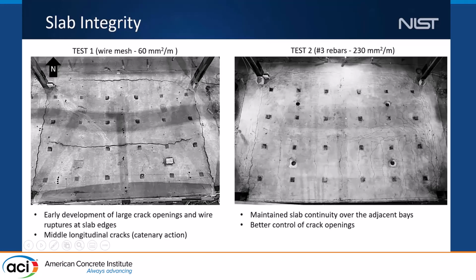Here is test number 2, reinforced with number 3 rebars in both directions. As you can see, there are small crack openings here and there, distributed everywhere, including some on the transverse and longitudinal lines and everything. But it maintained the slab continuity very well during the fire exposure.